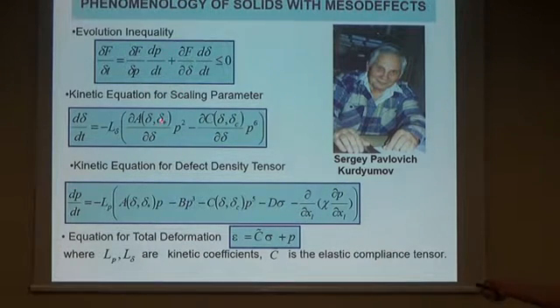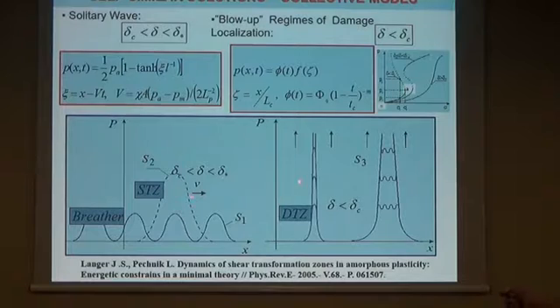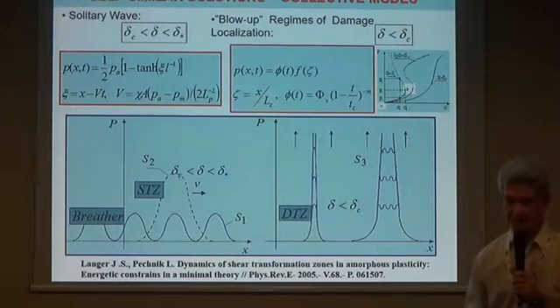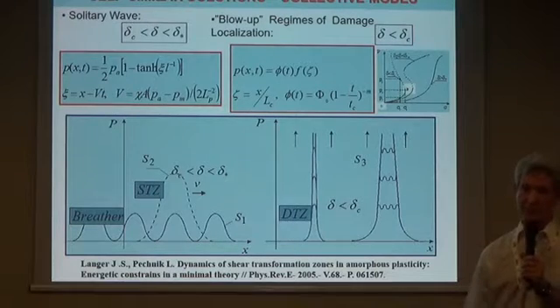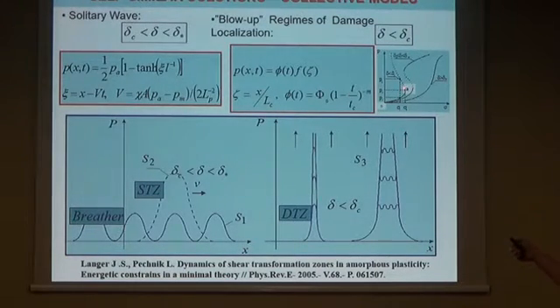We studied these properties in terms of constitutive flows, and a very important step was the self-similar solution established by Sergei Pavlovich Kurdyumov for the kinetic equation for the defect density parameter. The consequence was that in different ranges of nonlinearity, we have very specific self-similar solutions for defect density that change damage evolution. When we pass these critical points, damage-failure transition is a consequence of the generation of specific collective modes that have a blow-up nature.